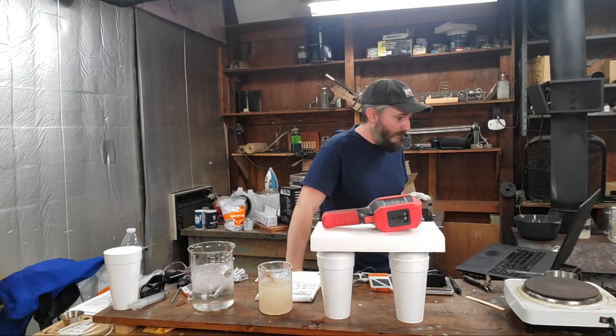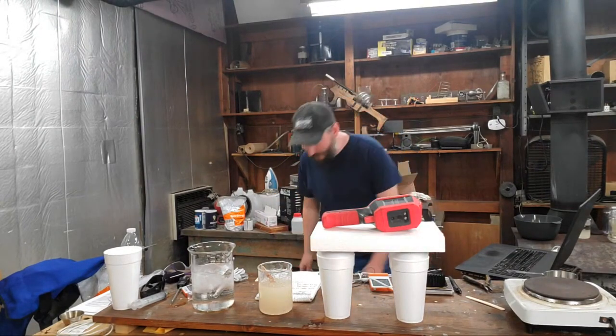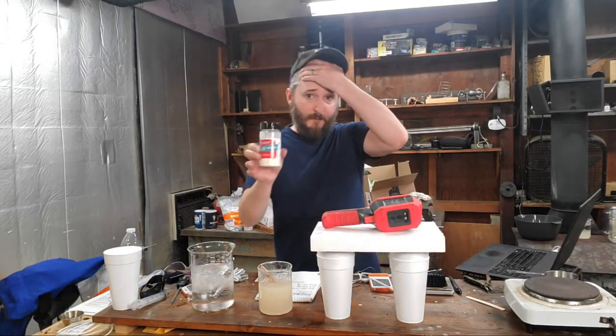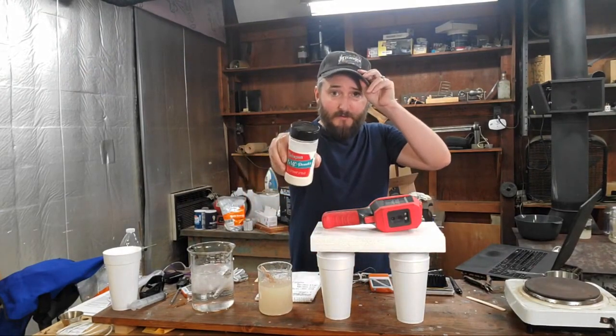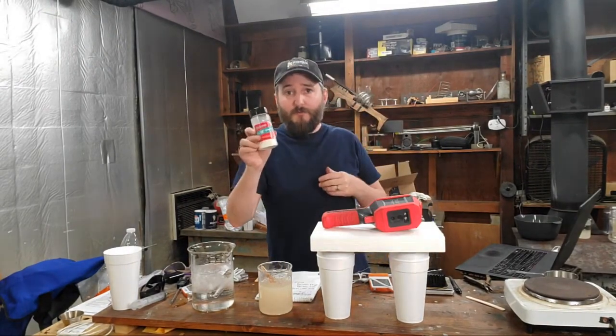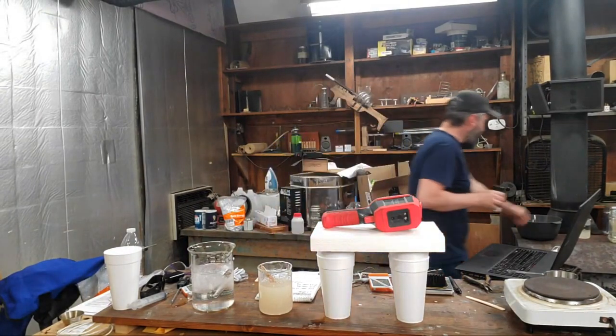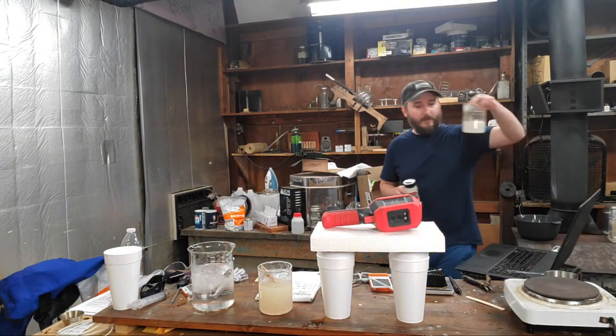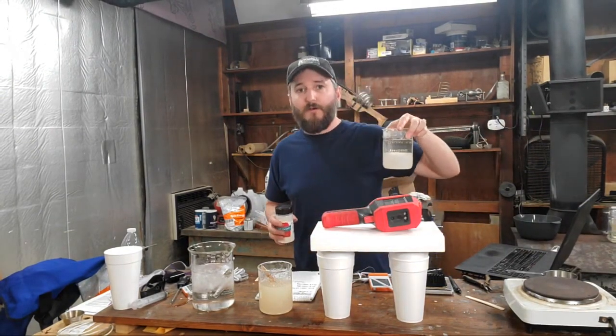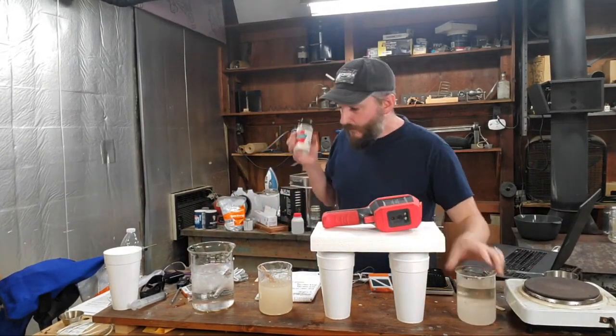The gelling agent that I use, CMC, is a good one, carboxymethyl cellulose. This has been used in a number of papers. You can get this online. Can you see that? CMC powder. This is not what I'm using in this one, but this is what has been used in a lot of research papers to prevent the crystals from settling. As you see in this sample here, it prevents those crystals from settling out, so you don't get the layers of salt concentrations and your mixture remains uniform.